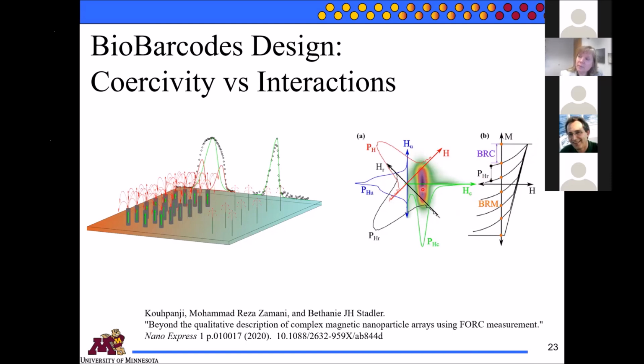And there's a way to plot out the coercivity versus the interaction. But as you can see, it's a fairly complicated signature that you can get out of FORC. And there are a lot of different interpretations of the FORC to try to determine what the actual coercivity is and the distribution in coercivities between the wires or between any particle, and what the interaction field is and its distribution. So with these sheared loops, that can be a little confusing.